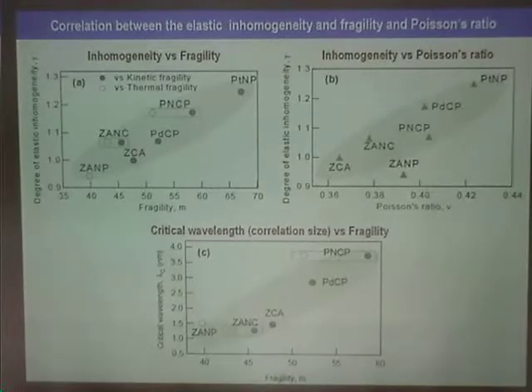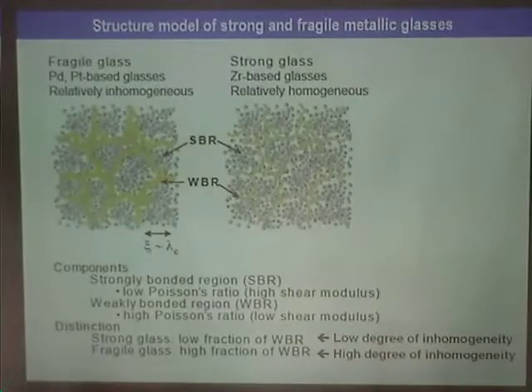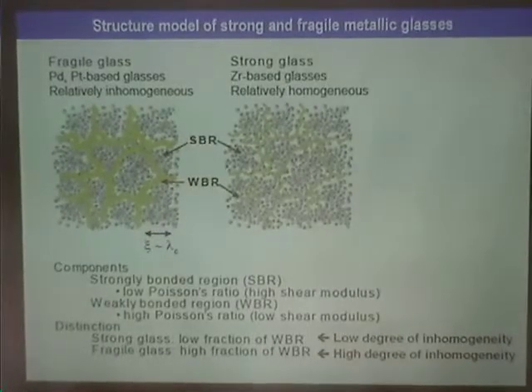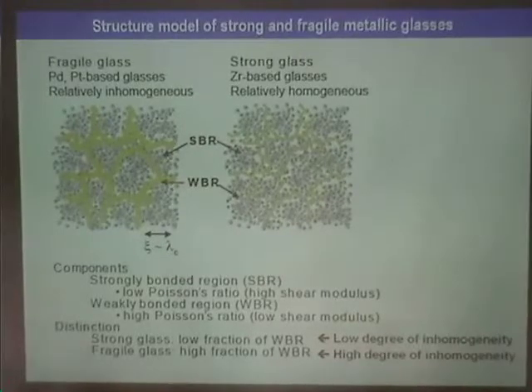Also, if I can ask a question, this critical wavelength lambda c, is that what you're proposing is the length of the strongly bonded region? Yes. In our experimental results, in the case of the fragile glasses, the weakly bonded region exists more than in the strong glass. In the case of zirconium-based metallic glasses, they are more homogeneous.